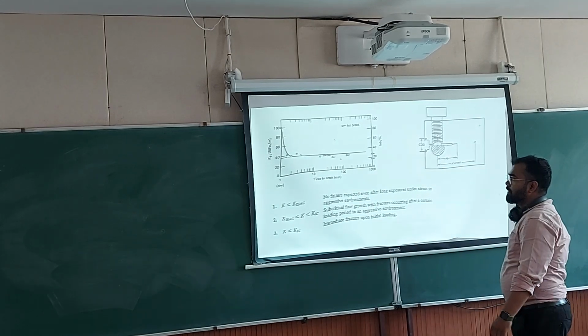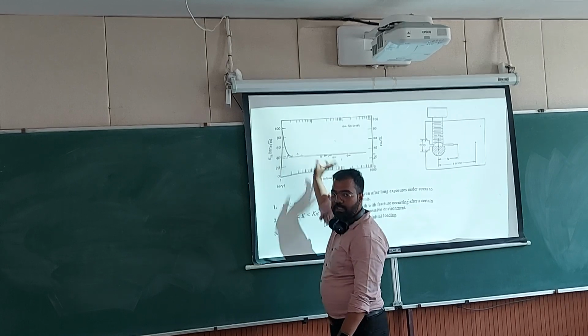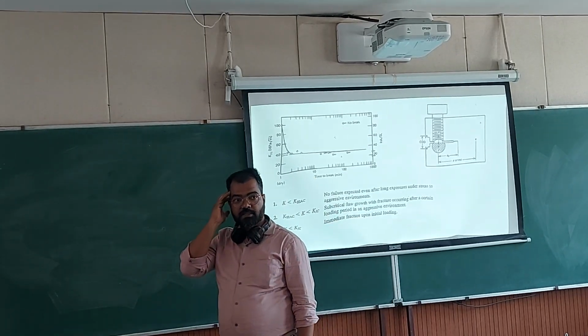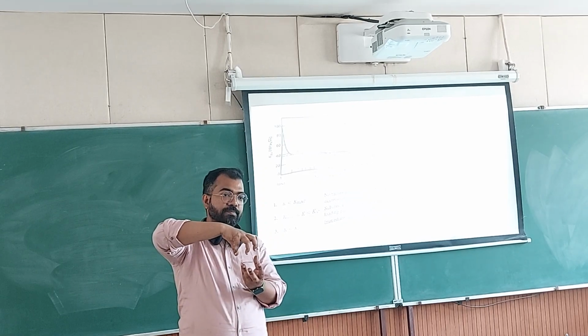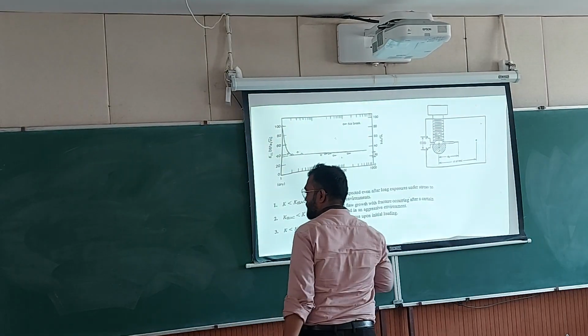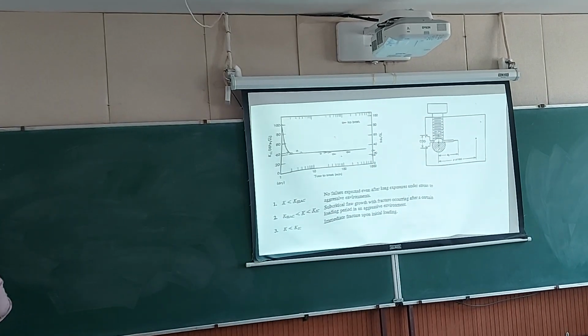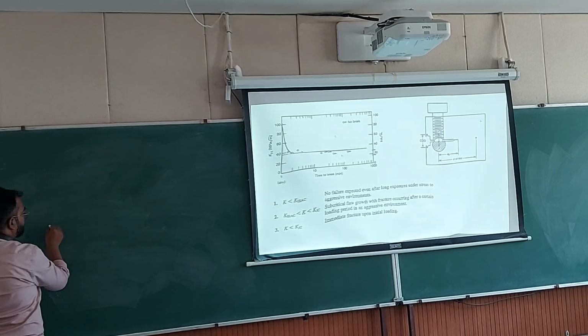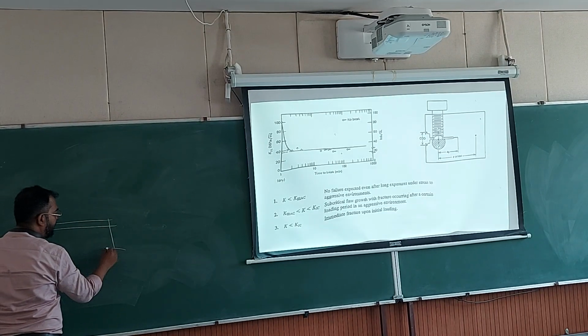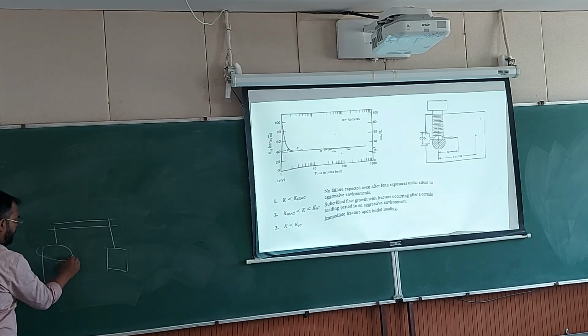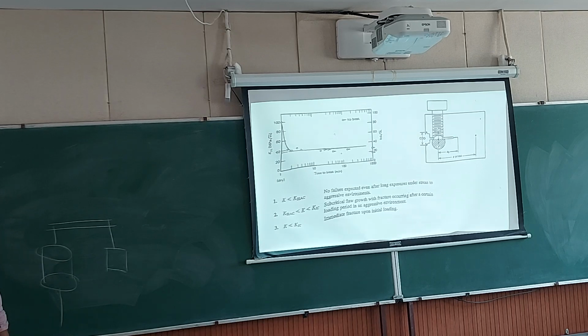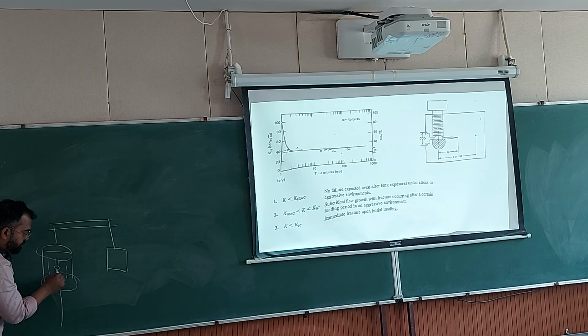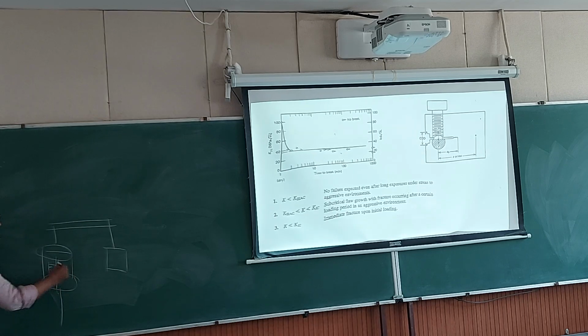And what is this? So in order to perform this test, you have to do a lot of testing and you will have to generate a lot of data points, right? So you put one sample in the specimen, okay, and this looks similar to the creep testing equipment where you put a kind of cantilever beam and you put a weight here and then you put an environmental chamber here, and in creep you had a furnace. Here you have an environmental chamber, and in this chamber either you put the corrosive gas or you put a corrosive liquid. Okay, so for that you will have a container, then you create vacuum here, and in this container you have your sample, and here you have corrosive media if it is liquid.